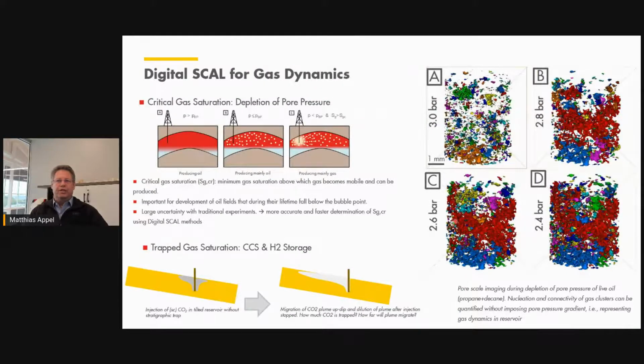That leads to very important applications. For instance, the determination of a critical gas saturation. Just as a reminder, critical gas saturation: when you deplete the pore pressure of a reservoir and you have a live fluid in it, then when the pore pressure goes below the bubble point, you will release the gas as a separate phase. And at some point, the saturation of the gas is so large that the individual gas clusters become connected, and then in that case you will start to produce mainly gas and you leave the oil behind. So huge economic impact on the evaluation to know what that critical gas saturation is. Now it's been done with experimental techniques for decades, but the problem is that experimentally the experiment will affect the result, because in order to measure it you need to impose a pressure gradient across the sample in order to get any flow, to measure what comes out of the sample.